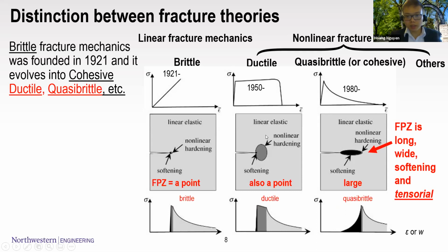However, in ductile material, surrounding that point and the linear elastic domain, there arises a nonlinear hardening. The nonlinear hardening comes from the plasticity of the material, and it also can affect how it interacts with the crack parallel stress. In quasibrittle material, that's another story. Instead of a ductile or nonlinear hardening region, you have a softening region, which is painted black here. And in this case, you have a finite domain of softening, and hence it also can suggest a change in the GF if you have an interaction with the crack parallel stress.